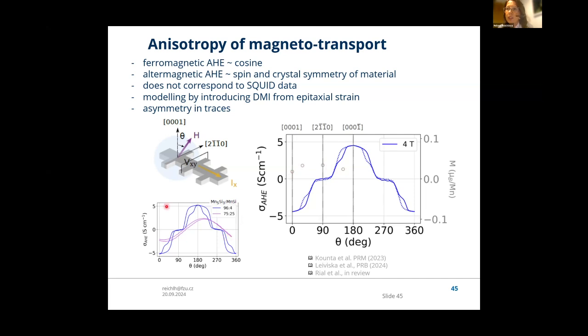And in this case we again combine the samples of high crystalline quality with the samples of poor crystalline quality, and our assumption is confirmed that the highly anisotropic anomalous Hall effect is indeed present only in the ordered crystal. In the poor quality samples, we are closer to what we would expect from the anomalous Hall effect in a ferromagnet, a cosine-like dependency.